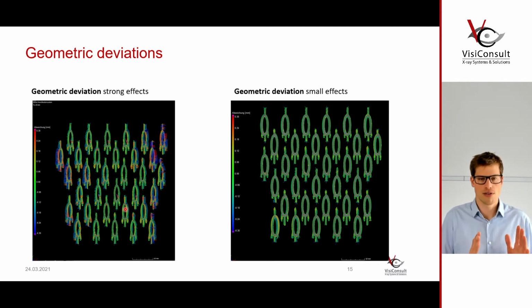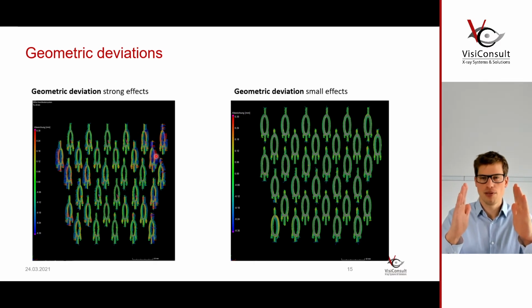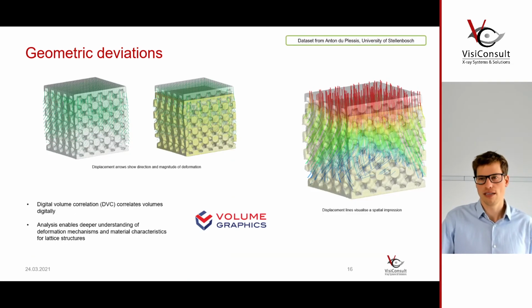This is classic because you build higher, so there is deviation inside the part, small ones. But significant is that on the two outside, on both sides of the outer area of that part, you see it leaning inside. And this can be compensated. So if you get that insight from your quality engineers, you could change the CAD towards a different design to compensate for that effect. And this is what you can do with a fully software driven approach, is that you can correct your build parameters according to the real outcome of your build. And this analysis helps you really to rapidly prototype and iterate a good part design.